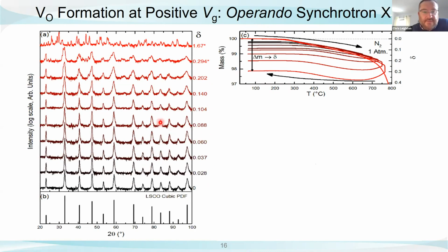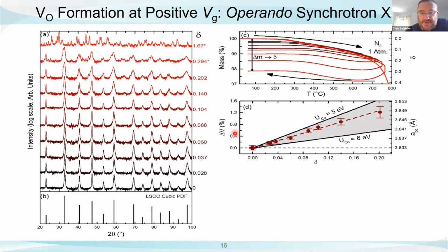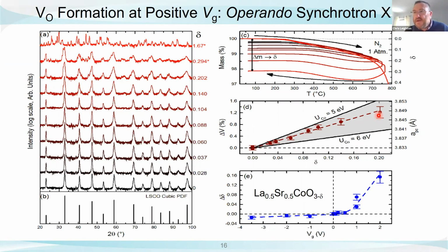We can then do powder X-ray diffraction, and we can pull out what is the change in the cell volume as a function of delta, the oxygen deficiency. And you can see, indeed, this is one of these many materials that undergoes this nice uniform linear expansion of the lattice when oxygen vacancies are formed. And the significance of this is that if we have an operando measurement of the cell volume versus voltage, and we now know how the cell volume responds to oxygen deficiency, you can just put those two things together and we can predict or estimate the change in oxygen deficiency that's being generated by the gate voltage. And it turns out with just 2 volts, we're already getting 0.16 missing oxygens per unit cell.